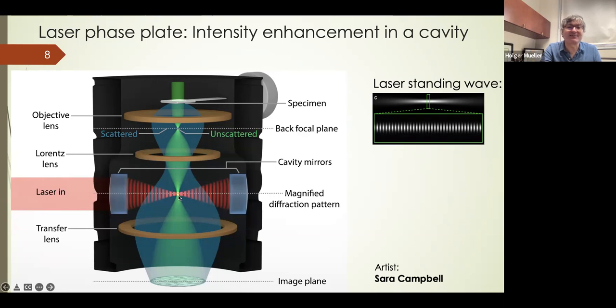So we use the Lorentz lens to generate a second diffraction plane down here, where we have more physical space. And this diffraction spot is about 5 or 6 times magnified relative to the original one, making it easier for us to integrate our laser cavity. So the laser enters from here to ultra high reflectivity, ultra low loss mirrors, builds up about 10,000 times the laser power and generates the standing wave pattern, and the central most bright spot, in theory at least, should interact with the undiffracted part of the electron beam.